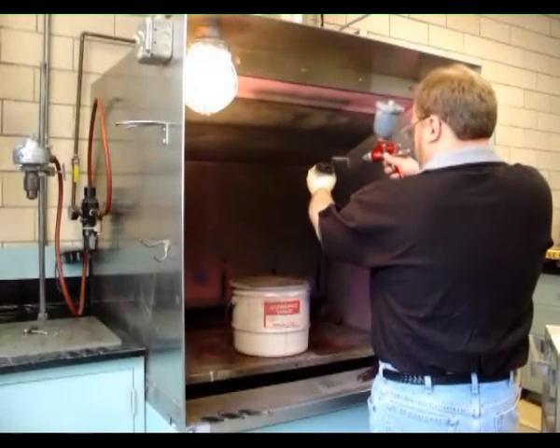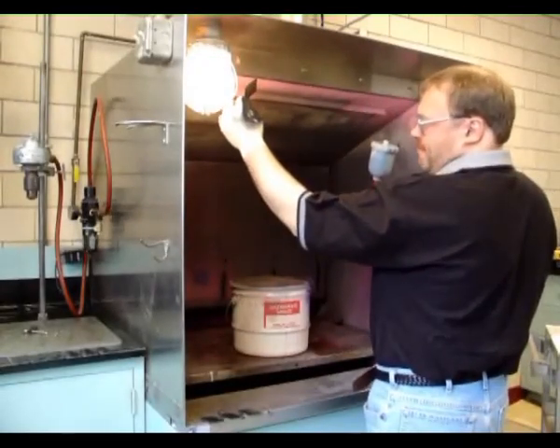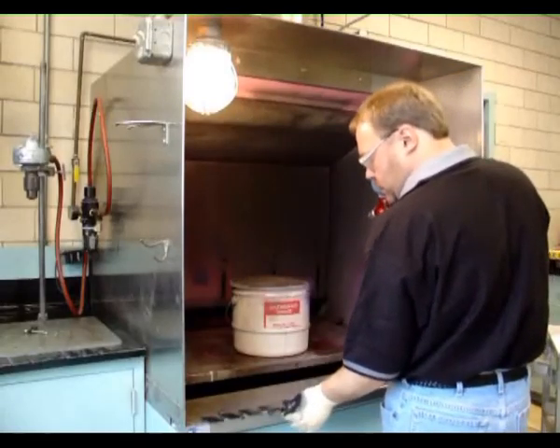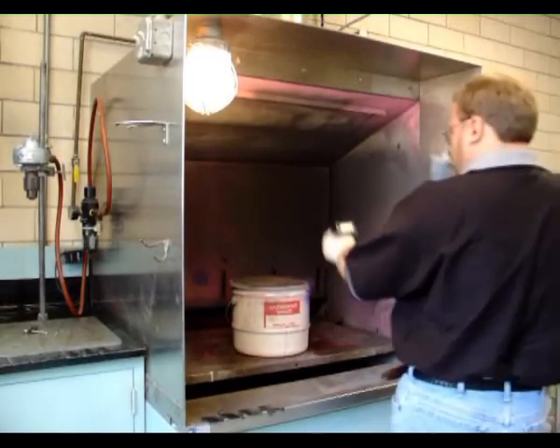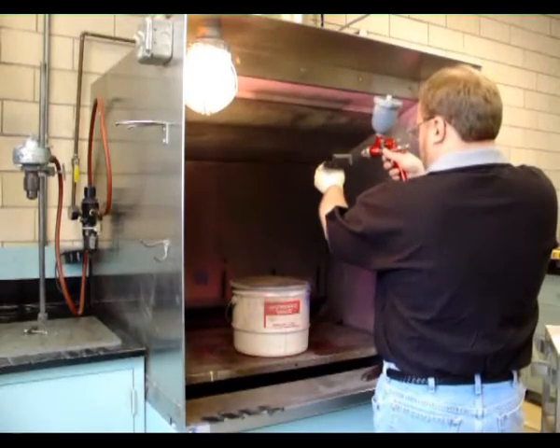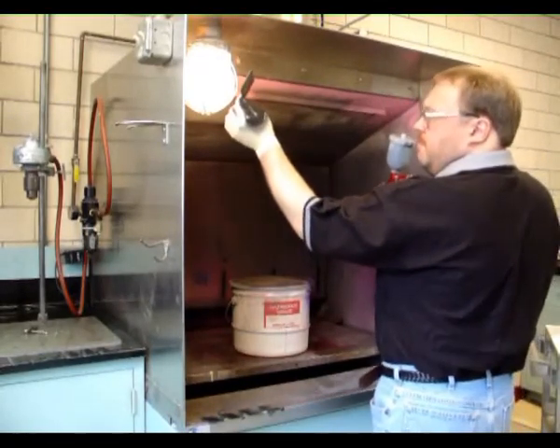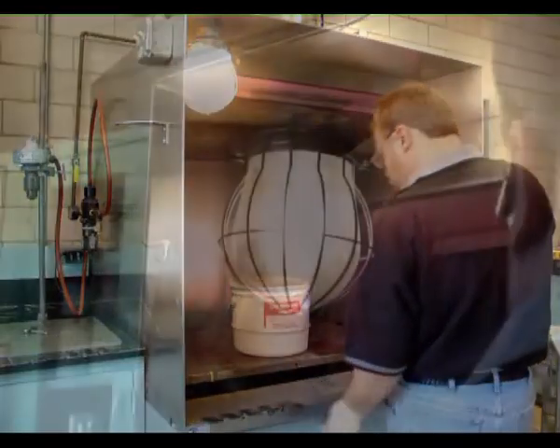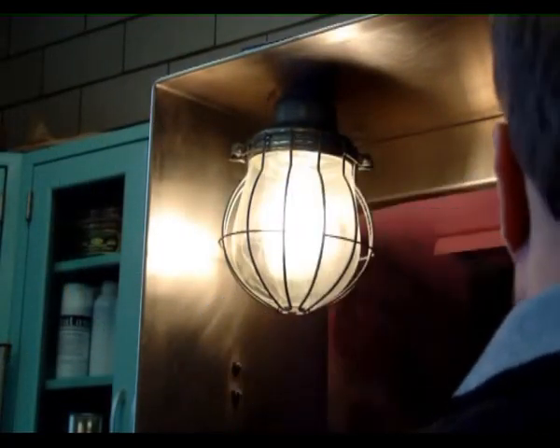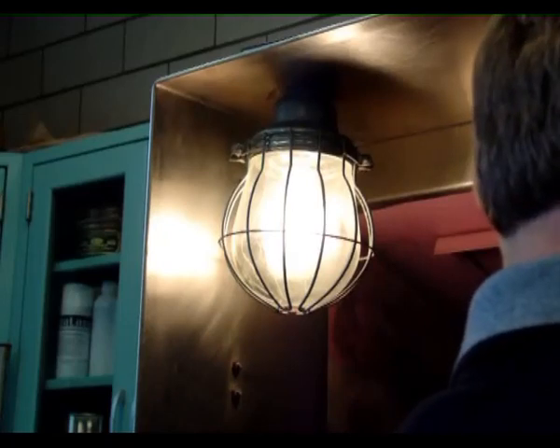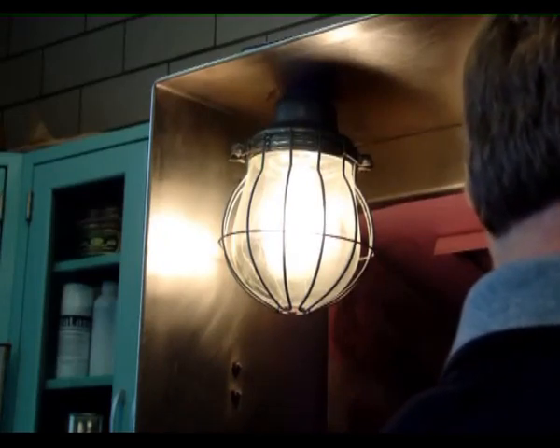Apply the marking material using a standard spray gun or airbrush. Apply using smooth, even strokes to cover the area to be marked with about 3 wet mils of material. This is about the thickness of a good coat of house paint. You can check this on glass by holding the piece up to a strong light. Apply the marking material evenly until you cannot see light shining through the glass.